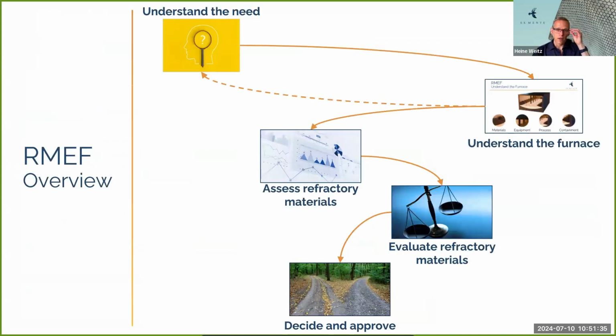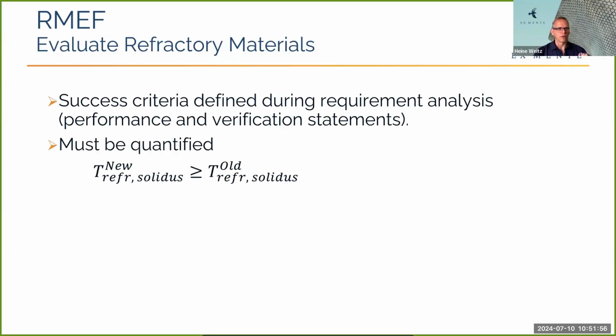Okay, we can then go into the evaluation of the refractory material. So now we will take these assessments and compare the results with the requirements that we identified initially. So I've got a bit of a flow chart here, well, actually, firstly, sorry, before I get to the flow chart, we would look at the requirements. In this case, we would look at the requirement that the refractory material solidus temperature for the new material needs to be greater than that of the existing material. So with thermochemical calculations, we can identify what the solidus temperature is and compare that with the original refractory material.